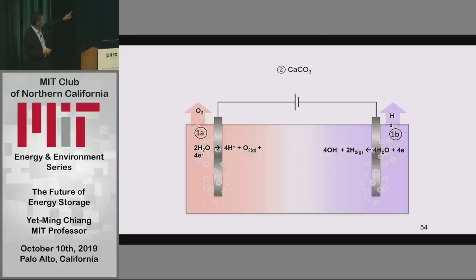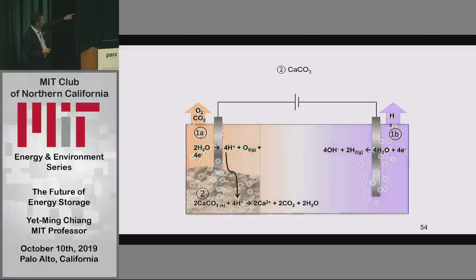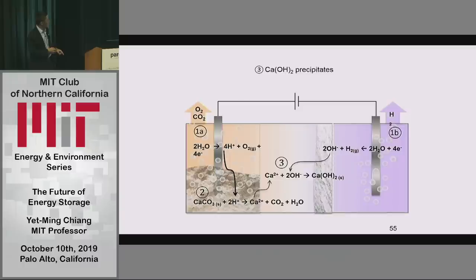Right? What we're going to do instead is to dribble in calcium carbonate on this side. Right? And it's going to dissolve. It's going to release CO2, just like your middle school chemistry experiment. That CO2 is now pure CO2 mixed with pure oxygen. Right? That mixture we can deal with because it's easy to separate. Right? This releases calcium into solution. And then from the right, we have a highly basic solution. And so calcium and OH together form calcium hydroxide. Right? That's a white precipitate.